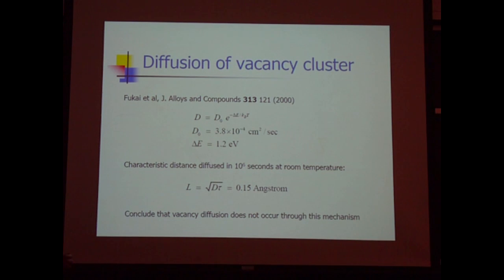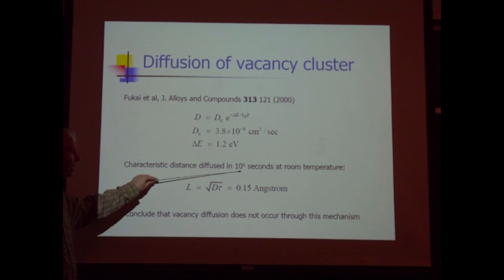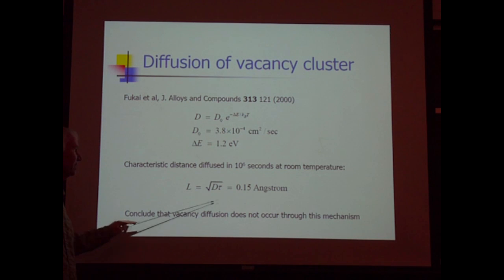Okay, so if we think about diffusion of vacancy clusters, that's been studied. Namely, we're imagining that in a cold fusion experiment, Fleischmann and Pons, we reach a loading of 0.95. We reach the magical physical chemistry regime where the vacancies become stabilized. We'd like to see our whole lattice turn into Fukai phase if possible. Now the headache is that at room temperature, the atomic self-diffusion is pretty slow. Fukai and colleagues studied vacancy diffusion and discovered a standard diffusion law with a barrier energy of about 1.2 eV. 1.2 eV in connection with diffusion isn't the world's fastest. Characteristic diffusion on a time scale of the order of 10 to the 6 seconds is 0.15 angstrom,